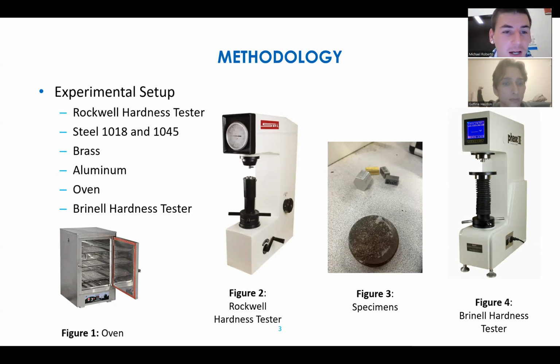During this experiment, we had a Rockwell hardness tester, steel 1018 and 1045, brass, aluminum, an oven, and a Brinell hardness tester. In figure 1 is the oven that we used to heat up the steel 1018. Figure 2 is a Rockwell hardness tester. Figure 3 is the specimens, and the circular specimen on the bottom is the one we used to make sure that the machine was running right, as it has known Rockwell hardness values, and we used that to test the machine and make sure that all the values were correct. From left to right on the top of figure 3, we have the specimens aluminum, brass, 1018 steel, and 1045 steel. And figure 4 is the Brinell hardness tester.